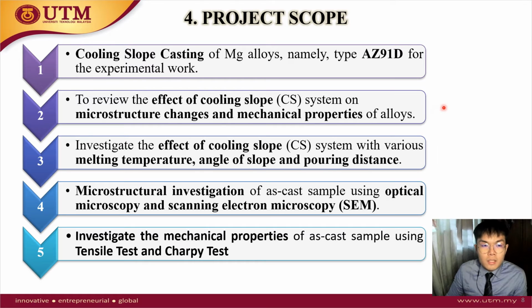The scope of this project includes cooling slope casting of AZ91D magnesium alloy, reviewing the effect of cooling slope system on the microstructure changes and the mechanical properties of this alloy, and investigating the effect of cooling slope system with various melting temperature, angle of slope, and pouring distance. It also includes microstructural investigation of as-cast sample using optical microscopy and scanning electron microscopy, and lastly investigating the mechanical properties of as-cast sample using tensile test and Charpy test.